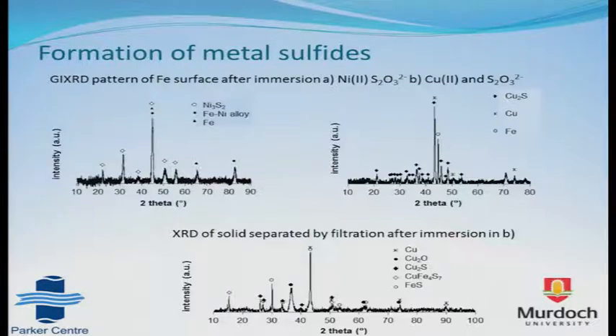But in solutions containing nickel and thiosulfate, I was able to determine that on the iron surface there was a Ni3S2 phase, possibly other ones which are not crystalline and weren't shown in the XRD. And also in the system containing copper and thiosulfate, there was the formation of a cuprous sulfide. And also, in this case, significant amounts are formed and they fall into solution as well and remain undissolved for an indeterminate time for the moment.